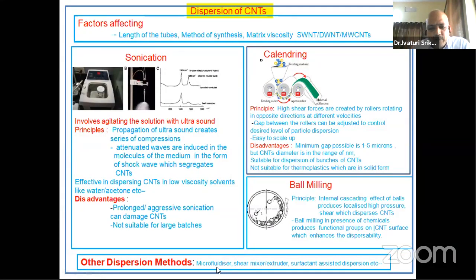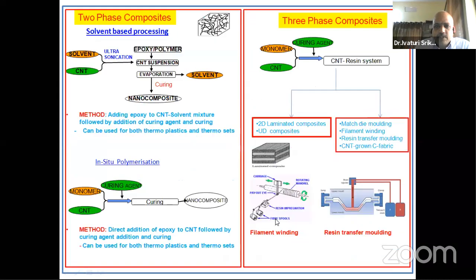Similarly, there are a number of methods like microfluidizer, shear mixer, and surfactant assisted methods. Surfactant means some chemical methods for dispersion. And ball milling is also widely used, which is a scalable method. In our lab, we have followed ball milling because it is the easiest to scale for dispersion. So this is about the purification, dispersion, and functionalization of CNTs.